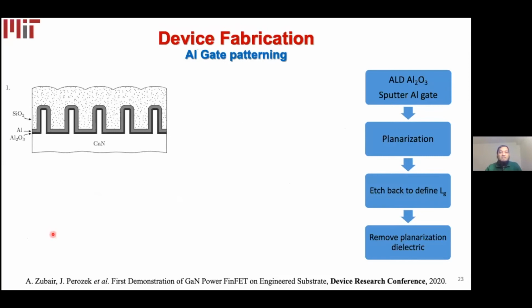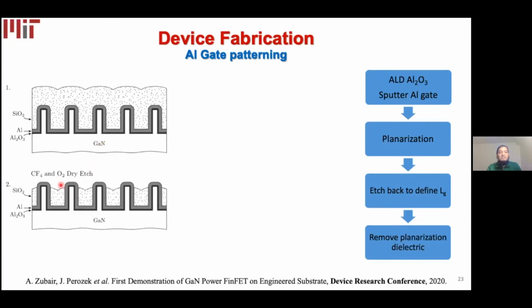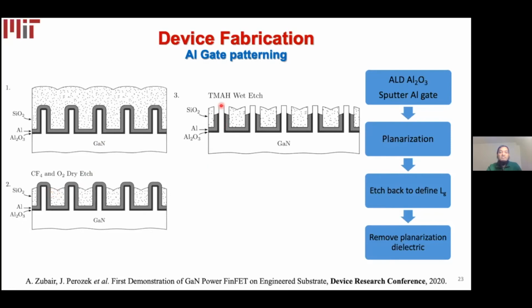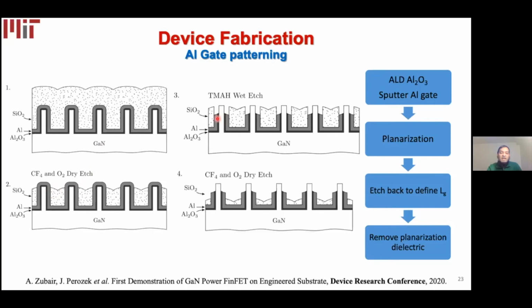As an intermediate solution, what we have pursued is an aluminum-based, wet etch-based gate patterning, where we use this TEOS PECVD silicon dioxide-based planarization. Then we etch back the silicon dioxide with a CF4/O2 chemistry. And once we have the desired height for our gate length, we use a wet etch to selectively etch the aluminum from the sidewall and define our gate length. And finally, we use a subsequent CF4/oxygen dry etch to remove the planarization dielectric, which in this case is silicon dioxide.